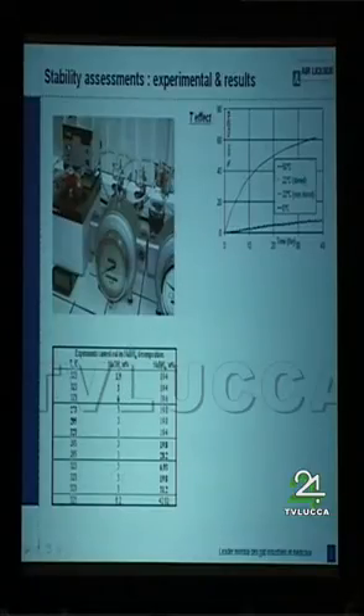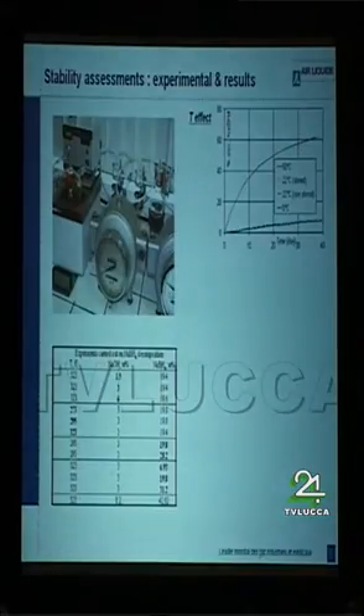First, for the temperature effect, here you have the percentage of decomposition of NaBH4 as a function of time: 10 days, 20 days, 30 days, 40 days. The blue curve, you cannot see it very well, is the decomposition at 0 degrees, so the solution is very stable at very low temperature. Here it's the decomposition at 22 degrees. The solution was stirred or not stirred, but there is no effect of that. As you can see, after 30 days, almost 10% of the NaBH4 was decomposed. At 50 degrees, the decomposition was greatly enhanced, and after 30 days, almost 60% of NaBH4 was decomposed in the solutions.